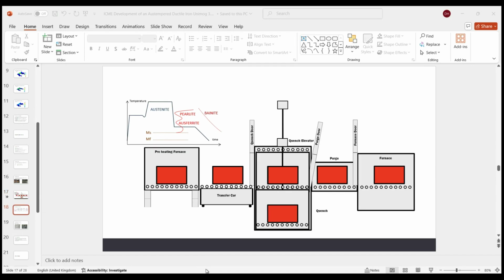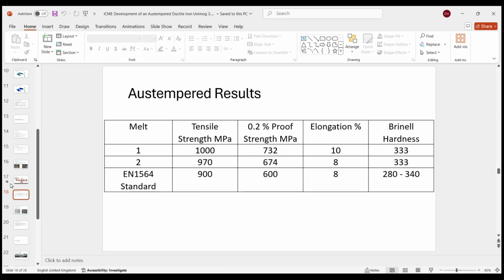Once we did our heat treatment on these castings, we then had to prove out the properties. As I said, there were 2 melts, even though I think there were only 10 castings made in the first order. We had about 1.89 nickel in one and 1.99 nickel in the other. And as you can see from the results, the standard is 900, 600, and we're achieving 1000, 732, 970, 674.